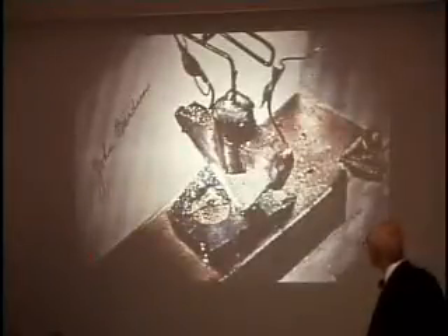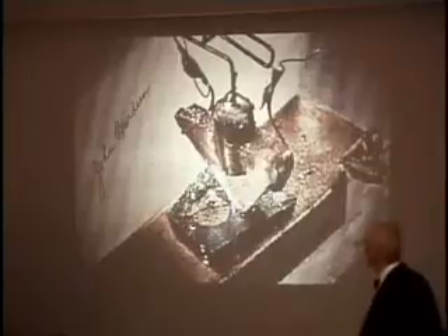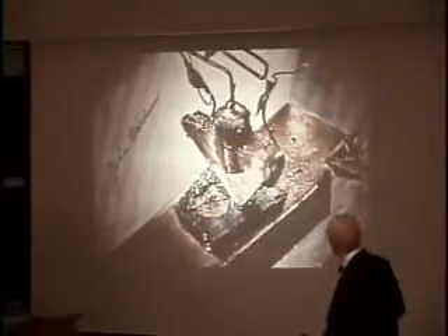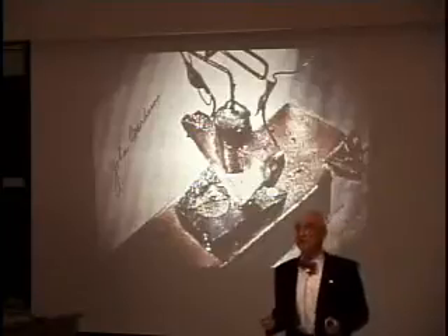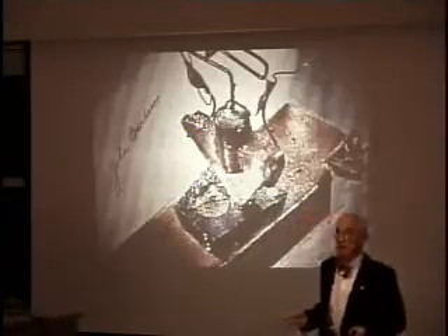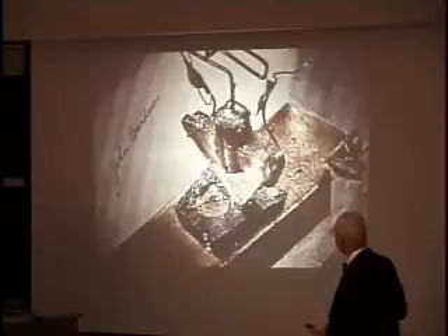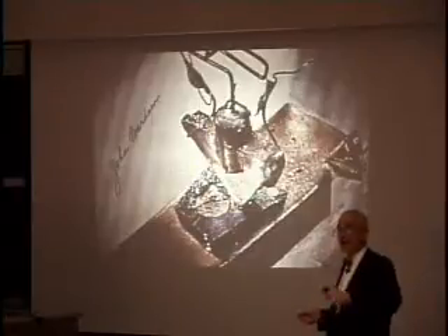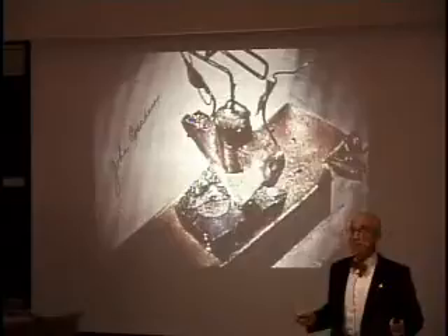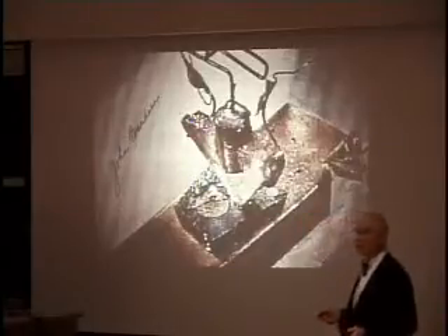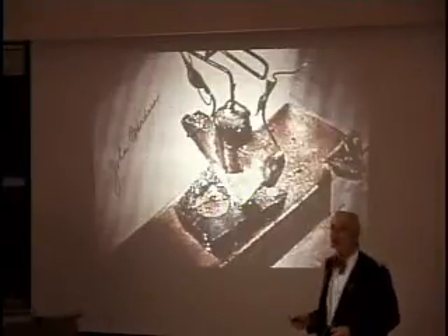Now, he knew and Walter knew about germanium, and they moved that experiment from silicon to germanium, and they put this gold pad here to try to get rid of the electrolyte. The electrolyte was slow, and that was not a good amplifier. So they put this pad here thinking it would be on the oxide and modulate the surface conductance underneath the oxide, and Walter was trying to open up a hole here where he had put the point contact for the spreading resistance, and some accident occurred. There was some spark or erosion or something, so Walter moved the point contact out to the side.